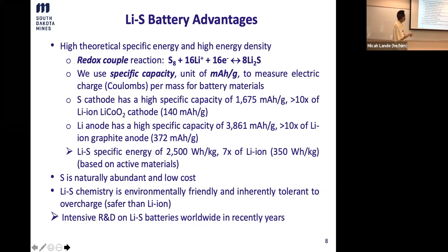So the sulfur cathode in this case has a high specific capacity of almost 1700, which is about 10 times the lithium-ion lithium cobalt oxide cathode. And the lithium anode has a high specific capacity of almost 4,000, which is 10 times the lithium-ion anode. So if you combine this together, you get the lithium sulfur specific energy of about 2,500, which is about 7 times the lithium-ion. So which is significant, right? That's why this is attractive.